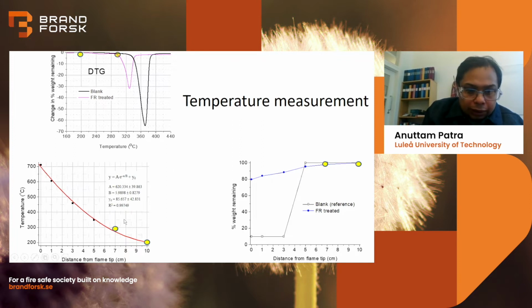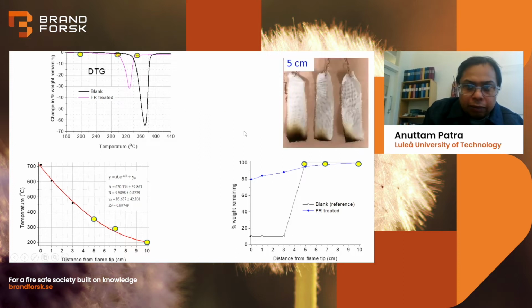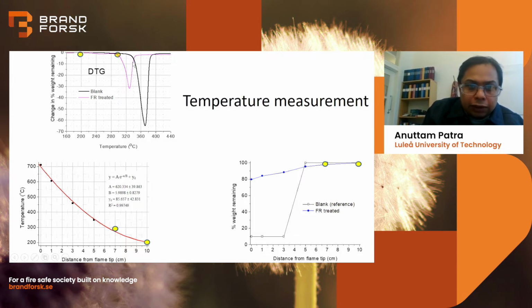If we bring the cloth closer to the flame tip, 7 centimeters from the bottom, the temperature rises to 300 degrees, which is at the onset of the decomposition temperature of the treated cloth. So in the graph, it decreased a little bit, but the untreated cloth is not affected.